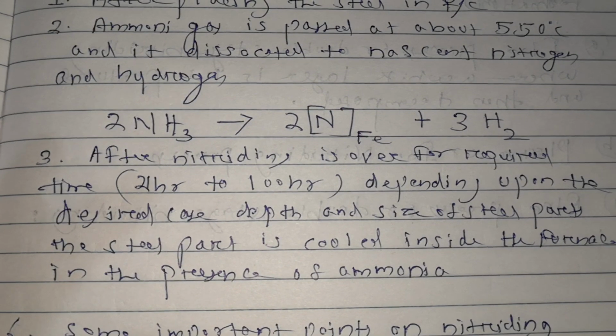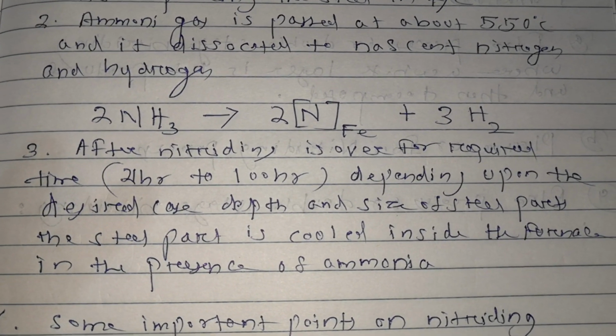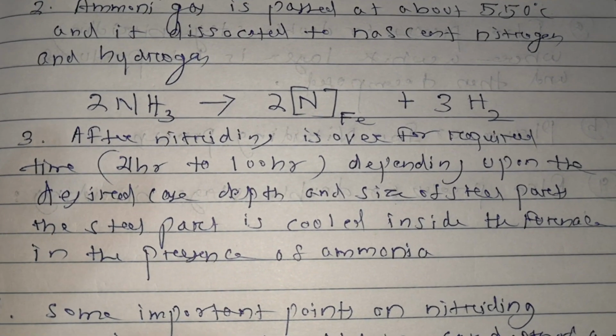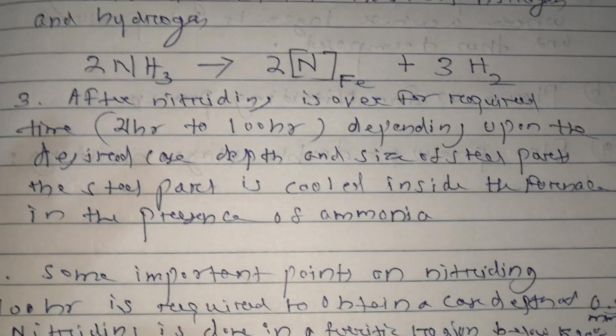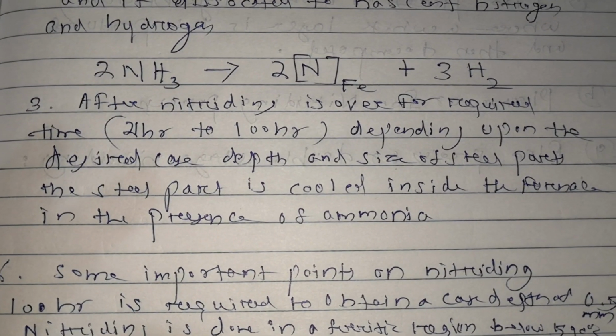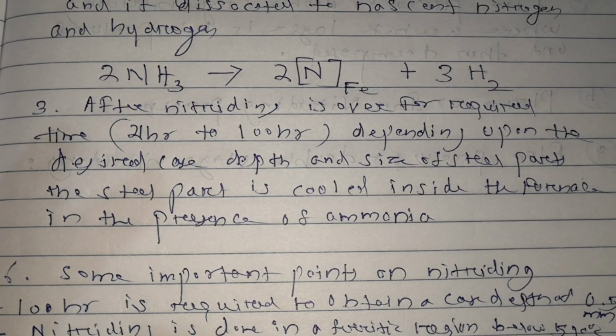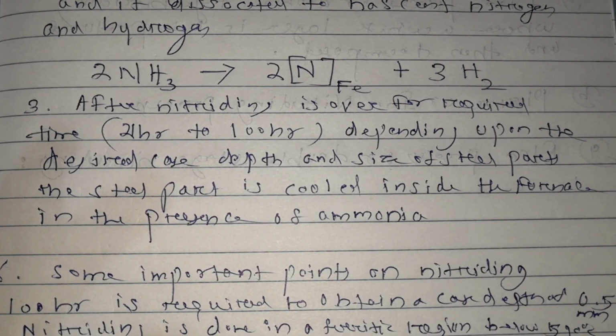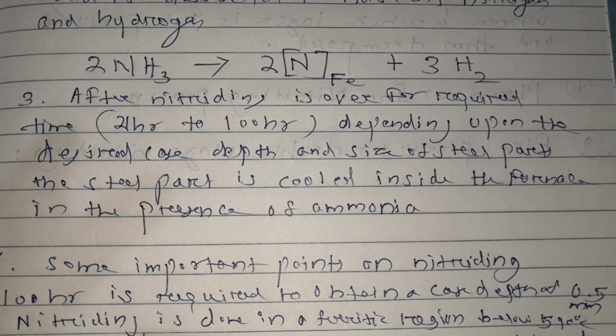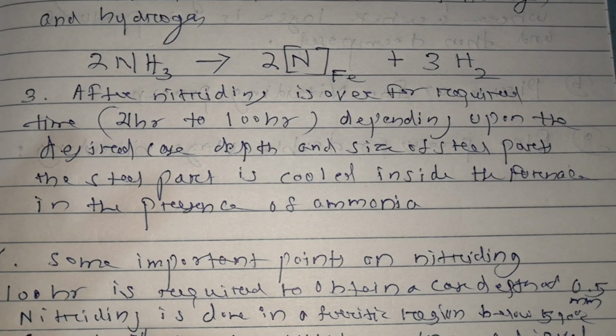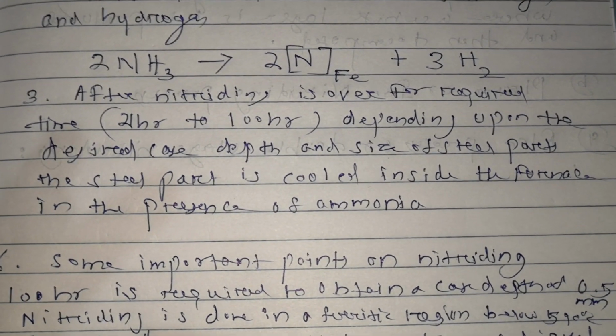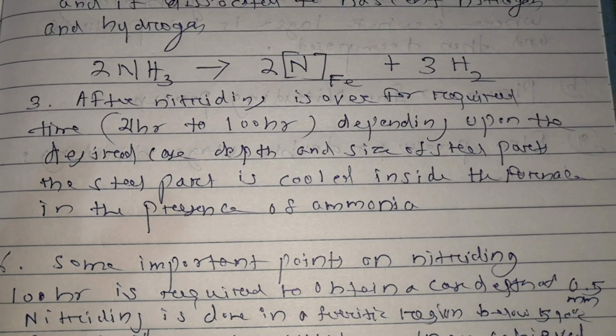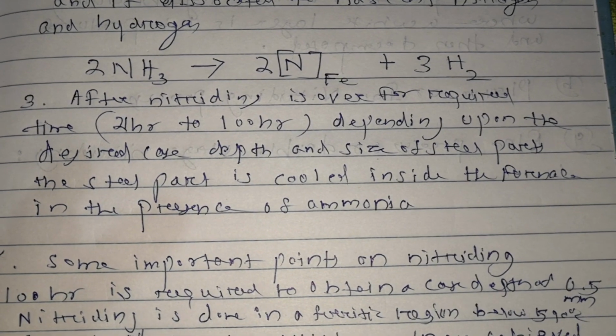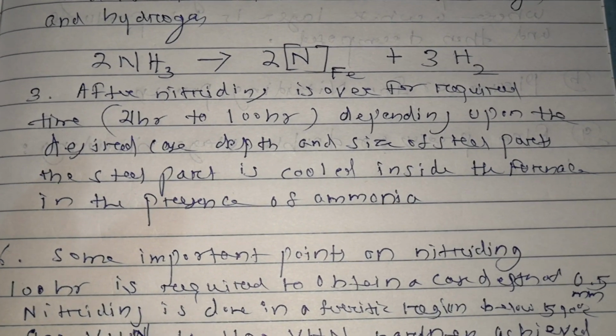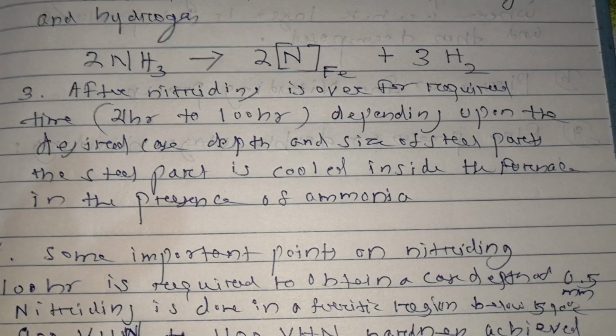So this nitrogen produced due to dissociation of ammonia diffuses into the steel surface. And after the nitriding is over, which can take 2 hours to 100 hours, depending on the size of the steel part and the depth which we want for nitriding, it is cooled inside the furnace in the presence of ammonia itself.